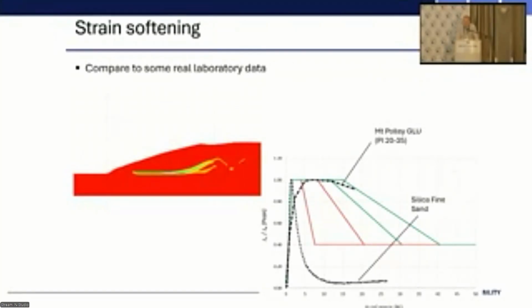And just incidentally, superimposed on that is some so-called real data, Mount Polley, that dashed line, that behaved very much like that less rapid loss in strength, whereas the Silica fine sand that I've referred to before yesterday, or the standard laboratory sand we use for a lot of our model calibrations, is even more brittle than the most left-hand of those curves.